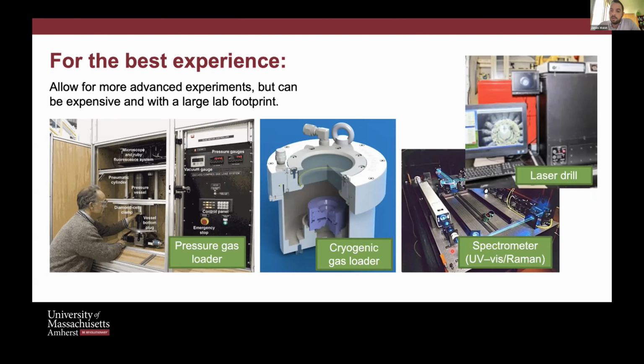And something that you almost certainly will have on campus, whether it's set up to look at DACs, may require some modification, is a spectroscopic table and some spectroscopic analysis tools, in particular UV-Vis, if you want to look at the R1 fluorescence of ruby as a pressure standard, or Raman. You can use Raman to measure pressure on the diamond edge, or you may want to measure Raman spectra of your sample. That can be a quick, more accessible way to do sample measurements. But of course, this is an X-ray diffraction workshop, so you probably want to see the crystal structure.